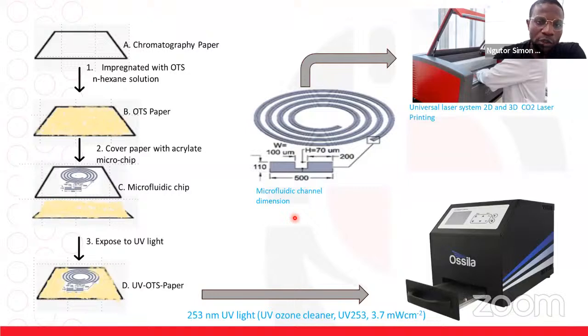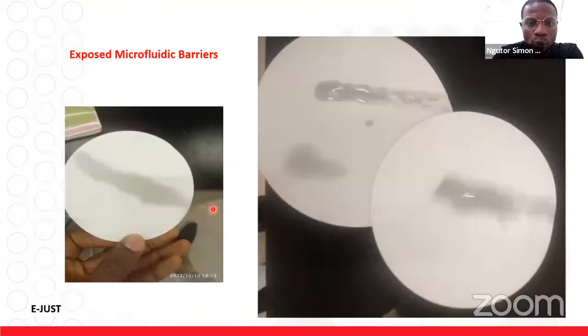We also use paper. We use chromatography paper. We impregnate it with OTS, and then disperse it in a hexane solution, and the paper turns like this. It becomes hydrophobic. When it becomes hydrophobic, you cover it with an acrylate. The acrylate, you can use it to make microfluidic channels, which you expose to UV ozone. We're basically using a 253 nanometer UV light, which turns the area you covered hydrophilic, and then you have your paper. The paper is good because it bases the technology on capillary action, so you don't need any pump. So this is what we expose, and this is what we have. These are the hydrophobic channels created. This is just an example to show you.